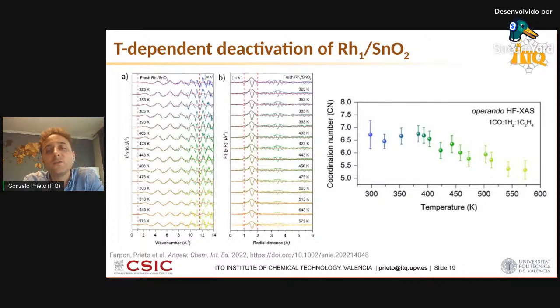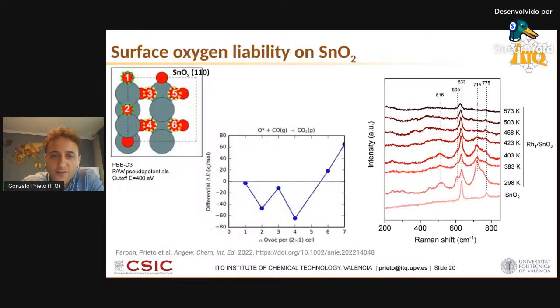What we did observe was a decrease in the coordination number of rhodium to oxygen in the first shell, especially when we were increasing the reaction temperature beyond 150 degrees C or so. That's the point where the deactivation started to be more severe. So we actually thought then that the oxygen surface chemistry of the tin oxide support could be responsible for both the unique catalytic performance of the system as well as its sensitivity to the operational temperature in terms of stability. And that's why we concentrated on investigating this surface oxygen chemistry on tin oxide, on which, by the way, there is already quite a lot of research done.